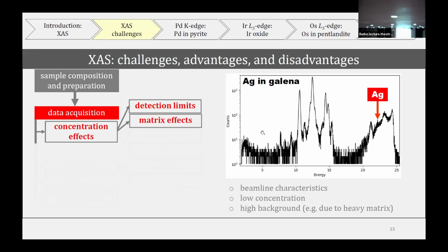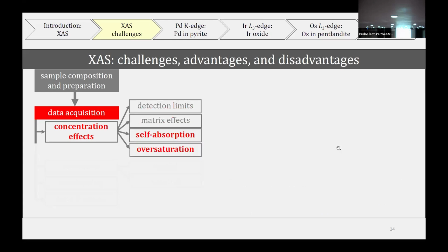Here, this is the XRF spectrum, and you see that it's silver in galena. This is the silver, our element of interest, and it's buried under the background, both because the matrix is very heavy, as it's lead in galena, and because the concentration of silver in this particular sample is extremely low. The next group of problems might come from the fact that the concentration is too high, unfortunately.